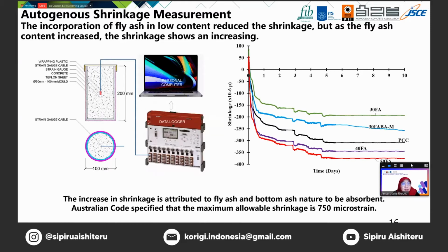And I put the embedded strain gauge in the center of the concrete, and we can monitor the shrinkage during the hydration of the concrete up to 10 days. As the ash content increases, here we add more water in the mixture, then the shrinkage increases too. But it is very surprising to see that the specimen with only 30% fly ash and the specimen containing bottom ash show lower shrinkage than the normal concrete.